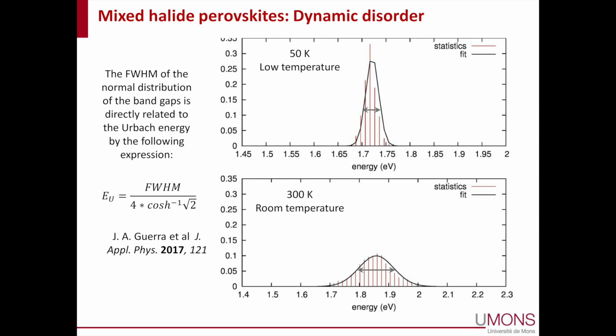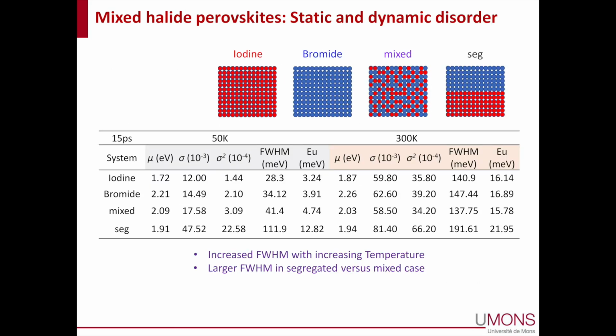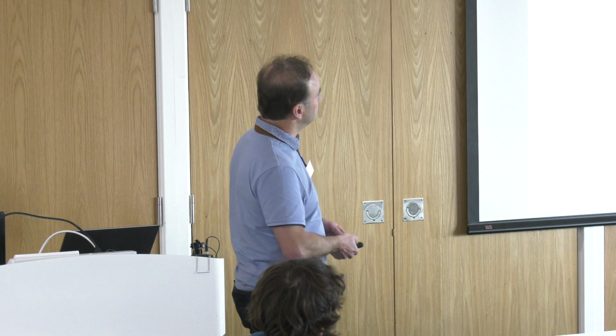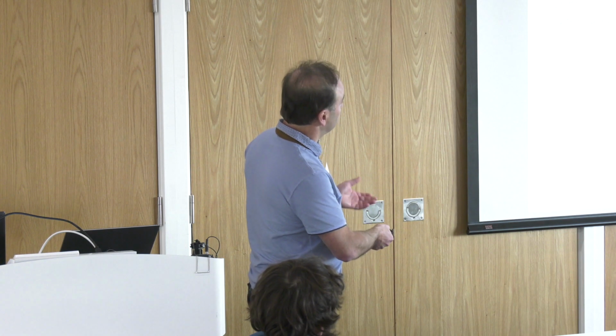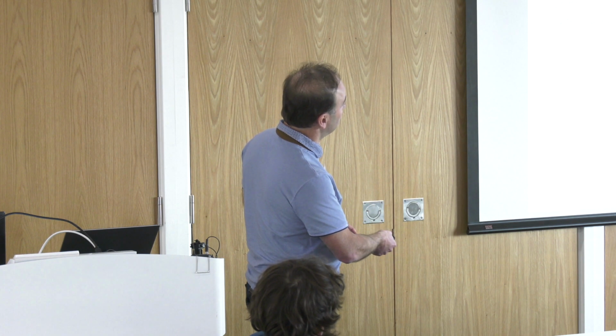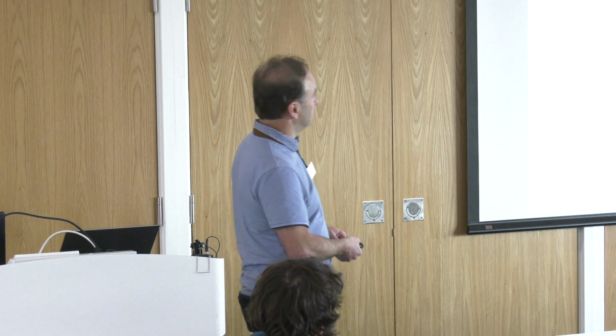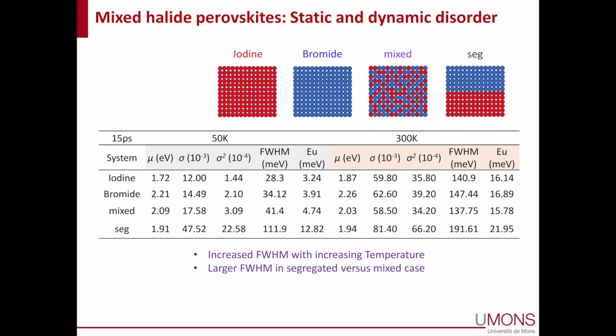And so you can translate this into a spectral line shape with a certain width, and from this width you can extract, using this formula here, the Urbach energy. So we did this for a number of systems, the purely iodine, purely bromine, and the mixed and segregated phase. These are very fresh data, so we still need to dig into the results in more detail, but what you see is, of course, the expected increase in the full width at half maximum, increase in the Urbach energy, going from low temperature to high temperature.